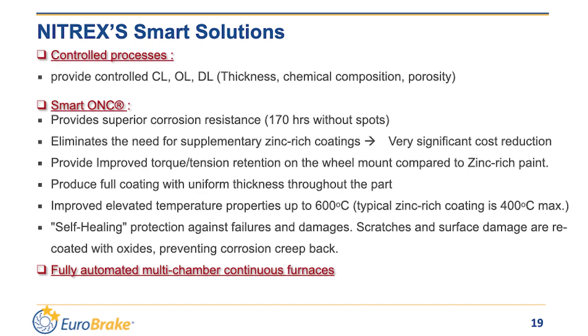It eliminates the need for zinc-rich paints, which highly reduces the cost, and it provides a full coating with uniform thickness throughout the parts, and it also improves the thermal stability, which is up to 600 degrees centigrade, compared to the zinc-rich paints, where the maximum that can be achieved is 400 degrees centigrade.